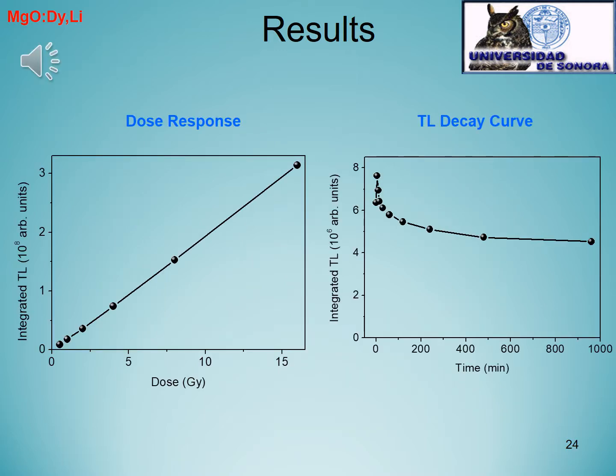As with the previous materials, we could observe very desirable features for this one, regarding the dose response and the TL decay curve, because the dose response was linear in the interval studied, and for the TL decay curve we observed this asymptotic behavior as a function of time, or storage time.